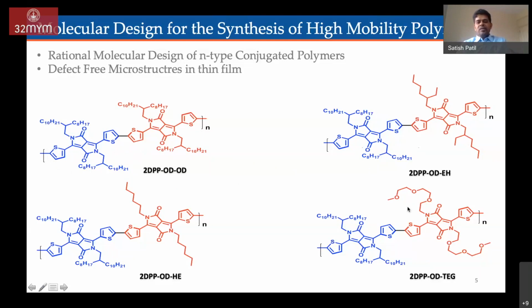So here is the polymer which has a very unique structure. The polymer has a similar backbone but a different alkyl chain. What we did is we functionalized these nitrogens with a hydrophobic, long alkyl chain, whereas on the other repeating unit of the polymer we put a triethylene glycol chain. So it's an amphiphilic polymer we made in the laboratory, and we asked this question: can this polymer be n-type? When I say p- and n-type, if you see the conventional semiconductor language, the pi conjugated polymers are predominantly p-type, and very few n-type polymers are reported in the literature.